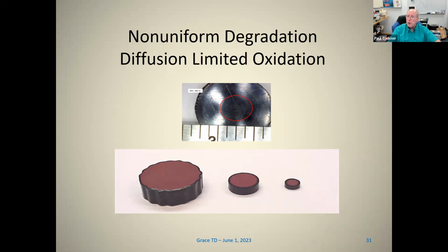And if you did this same thing with O-rings, you'd find that O-rings of the same diameter that were thicker would have better retained sealing force than ones that were thinner. If you had a material that aged uniformly, you'd find that the values are pretty much the same. So it's really important that you know the mode of degradation and how it affects percent retained sealing force.